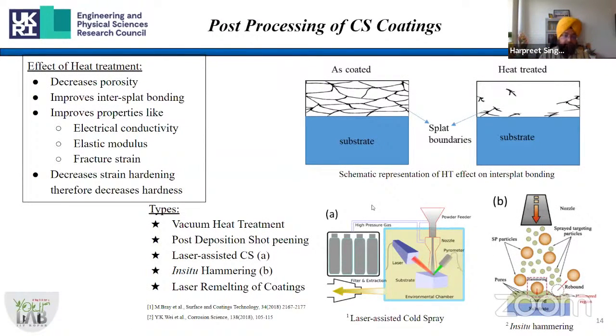So as I said, another aspect which we should not forget about cold spray coatings is the post processing, because usually they become very brittle due to that severe plastic deformation. So what are the benefits here? It can reduce porosity, it can improve inter-splat bonding, and it can improve properties like electrical conductivity, elastic modulus, fracture strain, and so on, and decrease the strain hardening, therefore decreasing the hardness. We could all imagine. I have seen in most of the applications, you have to go with some kind of these treatments.